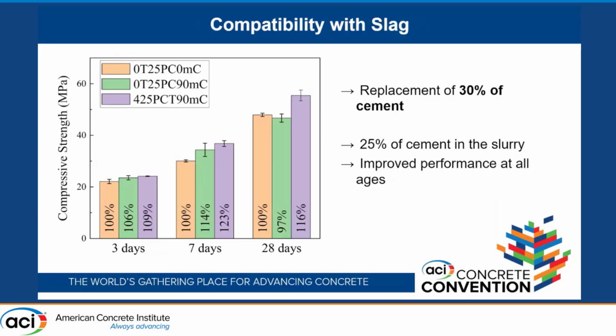And now looking into compatibility with slag. Again, all three samples have 30% of slag present in it, replacing the cement. And then we're following the same scheme: control, no carbonation and no tannic acid, followed by carbonation without the molecule, and then the last one, carbonation and the tannic acid present. In this case, you will see a slight improvement without the tannic acid, but once you add the tannic acid, you see that the improvement is even further, getting to 16% at 28 days. And again, no problems with the low early age strength as well.